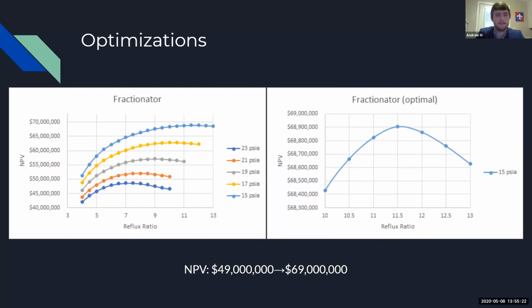And for a fractionator, we coupled the pressure of the fractionator, basically the feed pressure, and the reflux ratio. So we found that as you decrease the pressure, the NPV increases. So we got it down to 14.7 PSI or atmospheric with a reflux ratio of 11.5. And this brought our NPV up by 20 million, from about 49 million to 69 million.